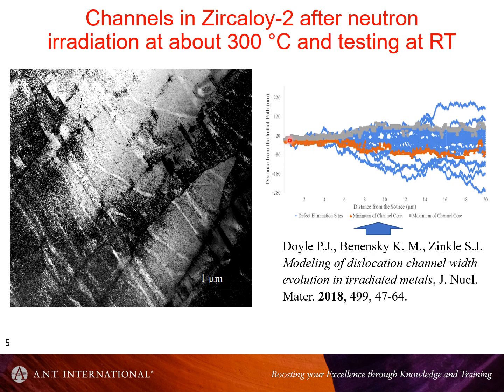yeah, call it slip band. Band is a misnomer, but a dislocation slip system is operating, and as it moves further, the volume of material over which the dislocations are active expands, much like a twin. But the shear is in this direction, and the strain is always perpendicular to the plane of the paper of the slide in this particular case.